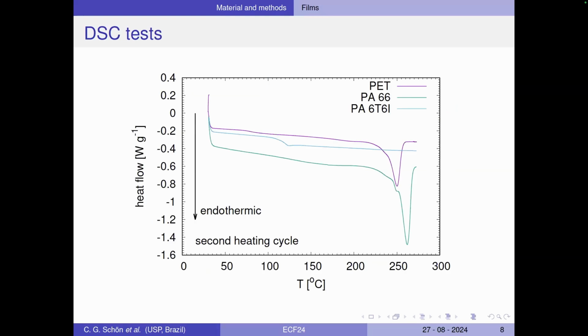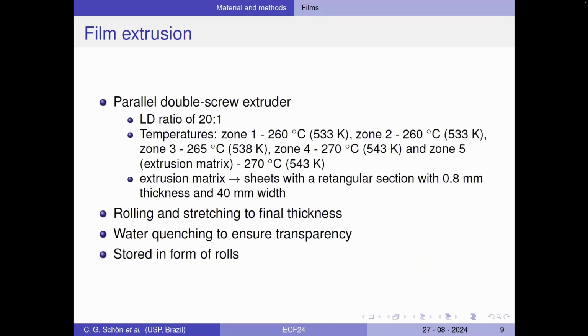We did, of course, a DSC of the base resins to set the temperature of the processing. And here are the settings for the extruder that we use to produce the blends. One important thing is that this is homemade, so we couldn't control very well the final thickness of the films. They ended with many thicknesses depending on the batch.